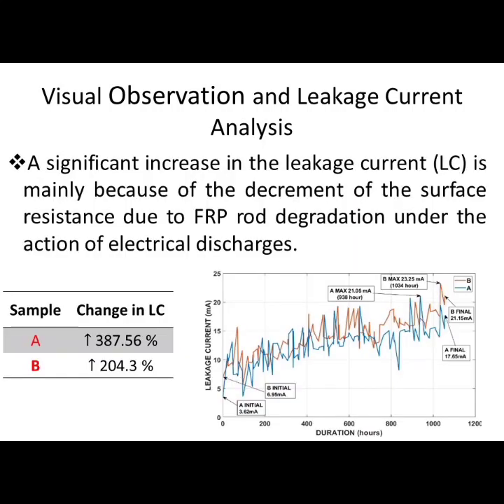This figure shows the leakage current of both samples during the experiment, where a significant increase in the leakage current is seen for both samples, which is mainly because of the decrement of the surface resistance as a result of the degradation of the FRP rod surface under the action of the electrical discharges.